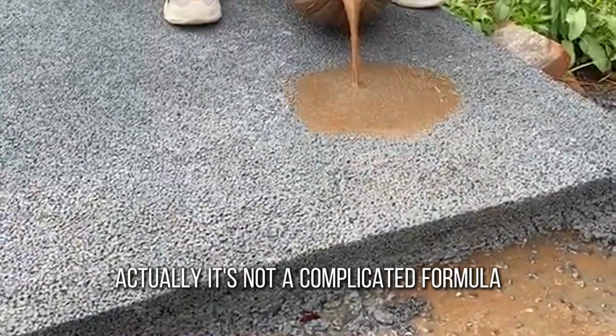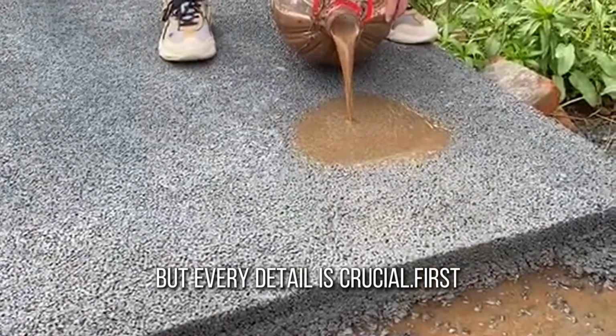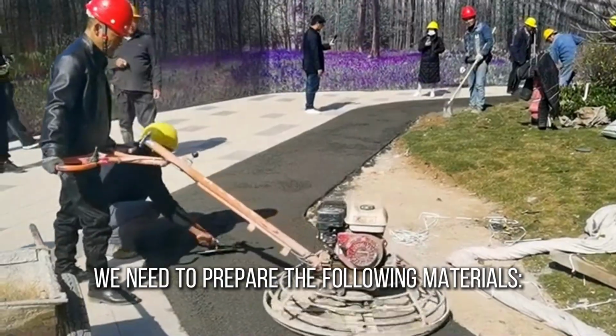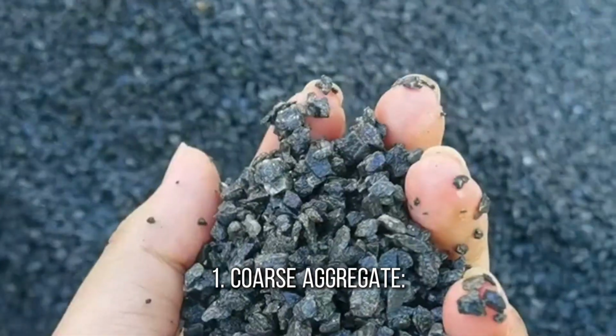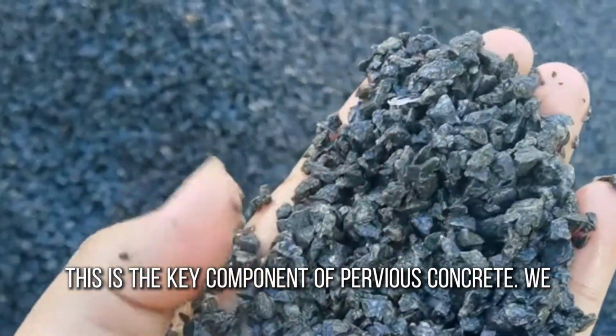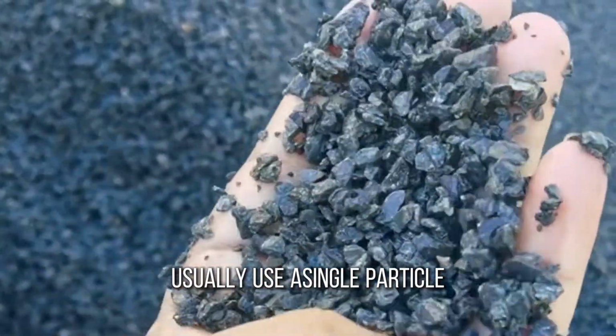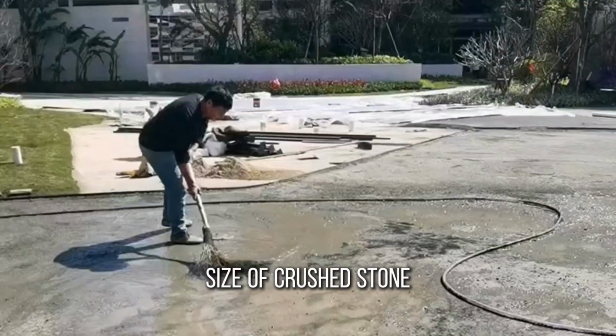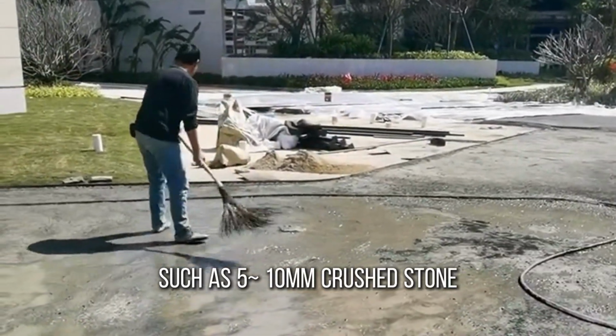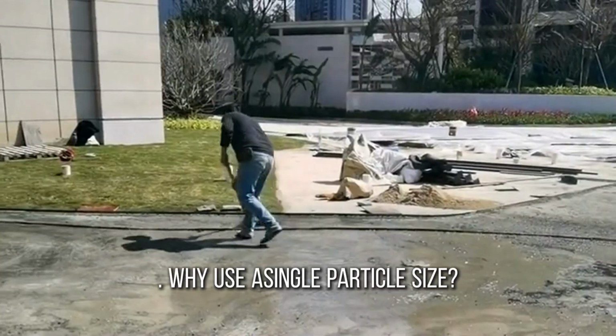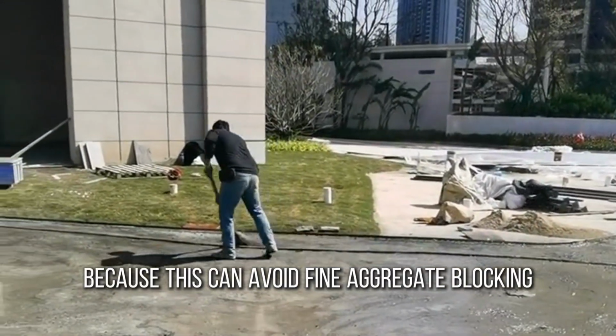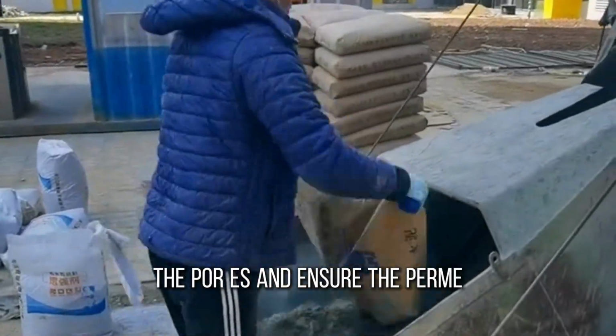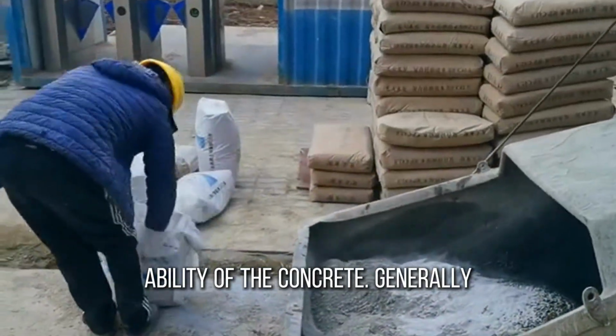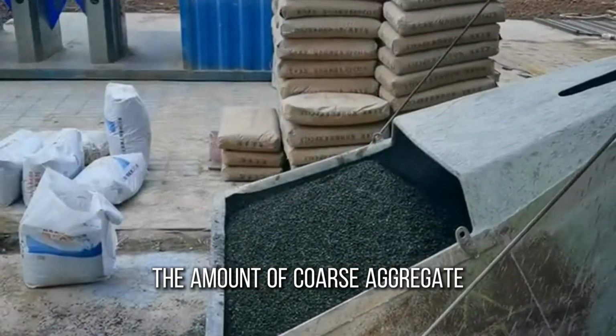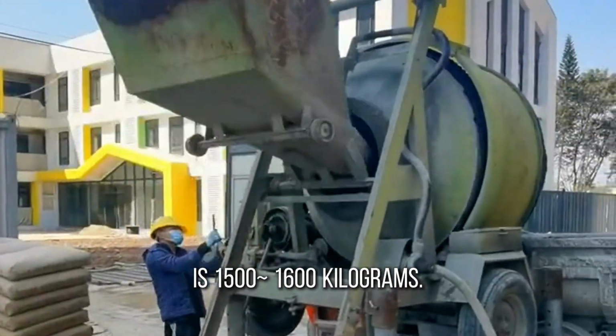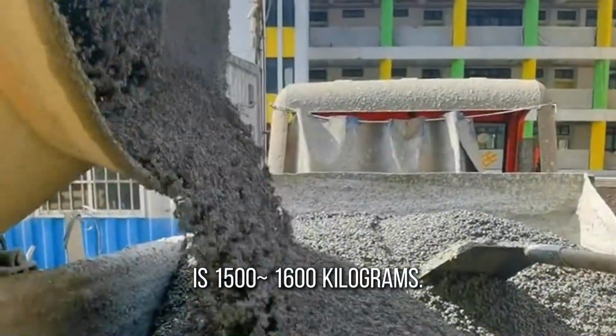Actually, it's not a complicated formula, but every detail is crucial. First, we need to prepare the following materials. 1. Coarse aggregate. This is the key component of pervious concrete. We usually use a single particle size of crushed stone, such as 5-10 millimeters crushed stone. Why use a single particle size? Because this can avoid fine aggregate blocking the pores and ensure the permeability of the concrete. Generally, the amount of coarse aggregate is 1,500 to 1,600 kilograms.